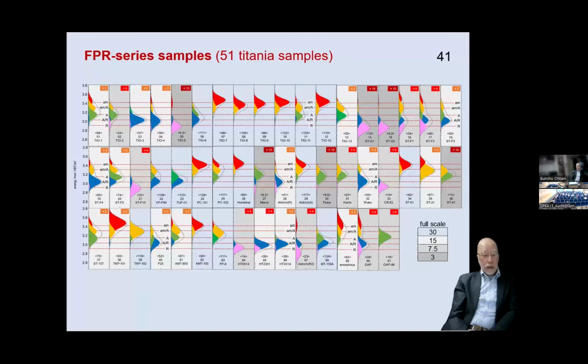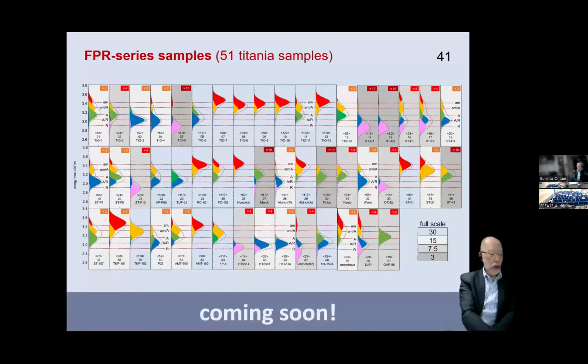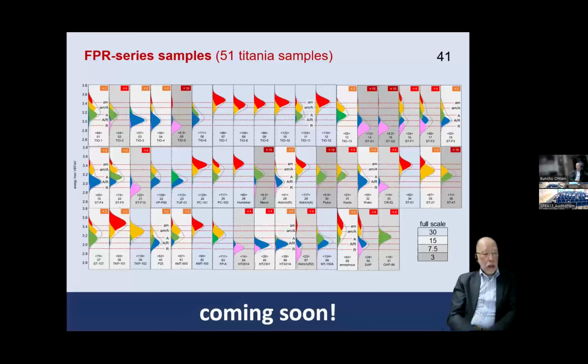And yesterday, the collaborator, Dr. Takashima, my son, interpreted this pattern, the AI or machine learning results of the analysis of those deconvoluted ERDT CBB patterns. And the full paper will be published soon. But today, I will show a small part. So the top one, in the center, you can see the large red peaks. That is the small anatase particles. Small anatase particles are almost covered with amorphous phase. The yellow one is a thin layer of amorphous, and the red one is a very thick layer of amorphous.